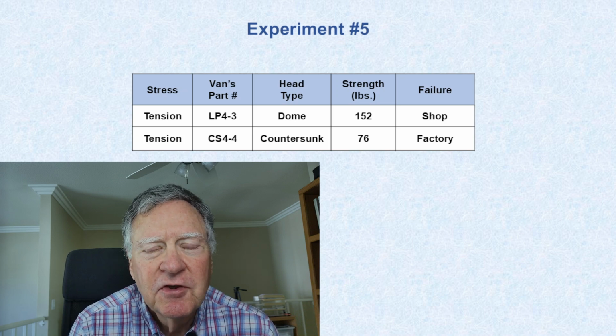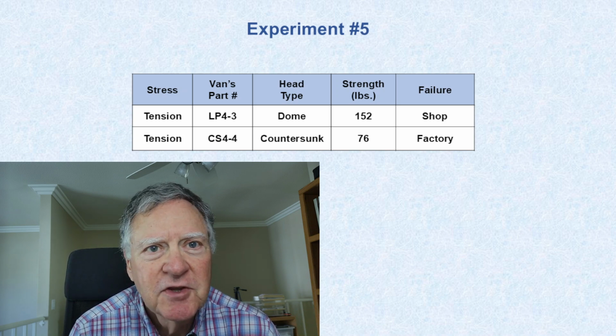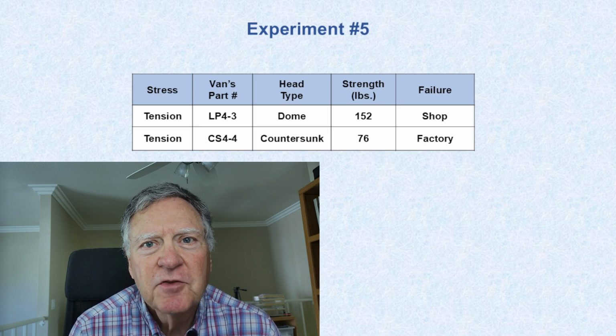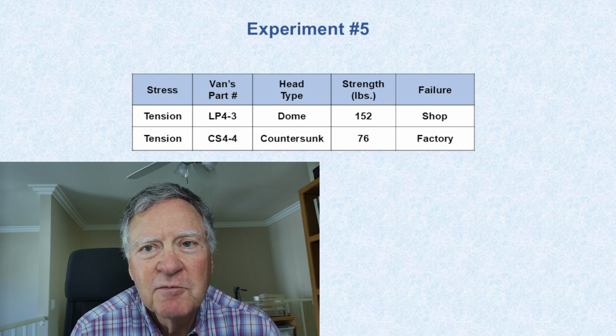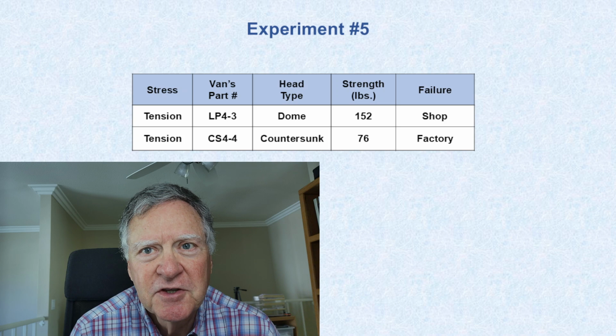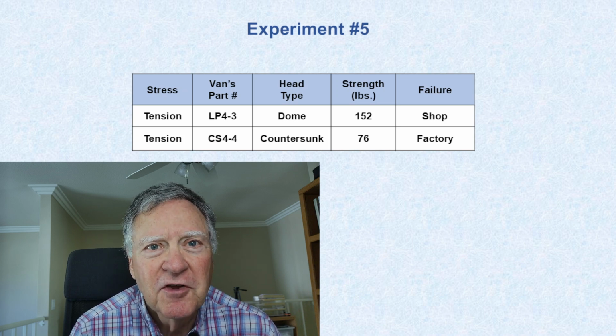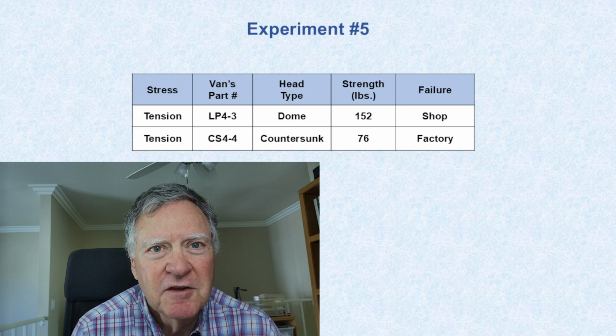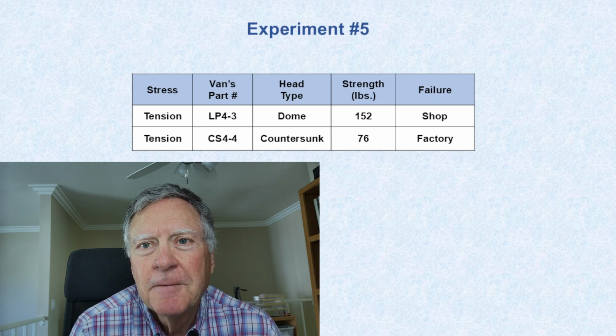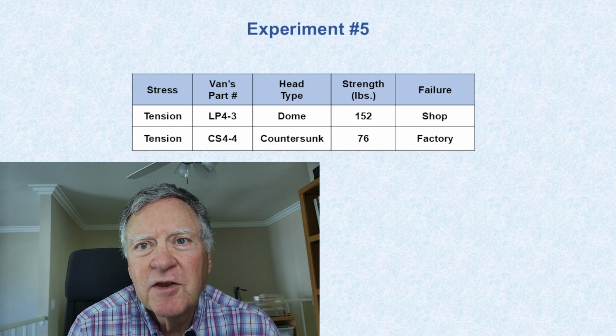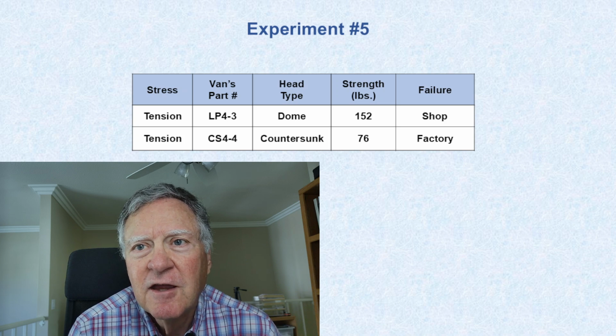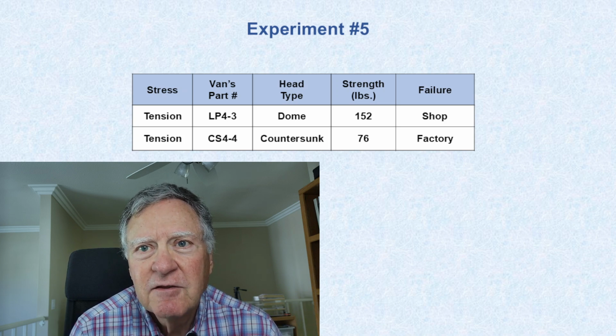And here's the results of my strength measurement. The LP 4-3 with the dome head was pretty strong. It was stronger than most of the solid rivets that I've measured. Of course, this is basically a number 4, a 1/8 inch rivet, and the solid rivets were all 3/32 or number 3 rivets. The strength was 152 pounds, and the factory head came out just fine. And the dome head, it was the shop head part that failed.